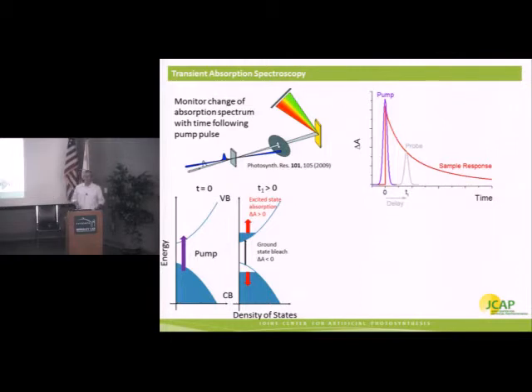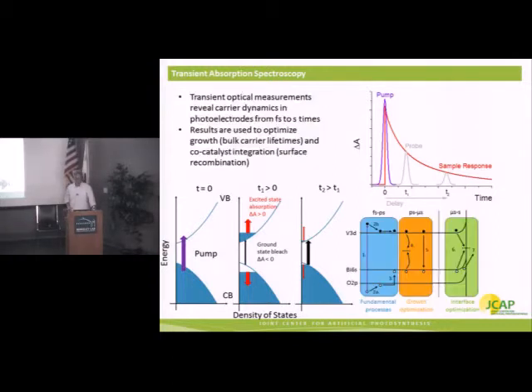Now, that's the origin of the signals that we see. But what we're also interested in is the processes that lead to recombination and relaxation to the ground state. So we're interested not only in what the spectrum looks like at a given time, but the time evolution of that spectrum. And so if we interrogate this now at another time t2, where the sample is relaxed further, we see that there's less electrons in the conduction band, there's less holes in the valence band. So these excited state absorption features have reduced over time, and the bleach at the band edge has now reduced as well.